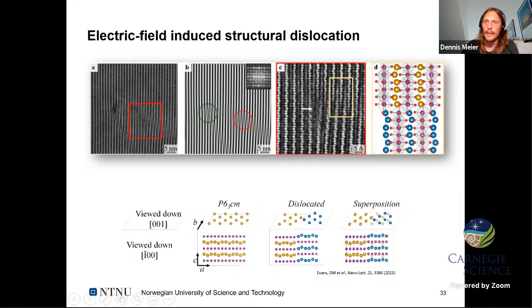This dislocated structure is in fact stable, which DFT calculations showed. It is energetically not too costly. It's about 7 times more than a charged domain wall that occurs in the system. So you just have to put the energy in to induce this dislocation, and then you can stabilize it within the material. And you see that also down here in this sketch, we have the normal structure with the erbium and the manganese layers. Then when we dislocate it by 1/4 along the C direction and 1/3 along the A direction, we get a stable state. And the superposition looks very much like what we see in our high resolution images.